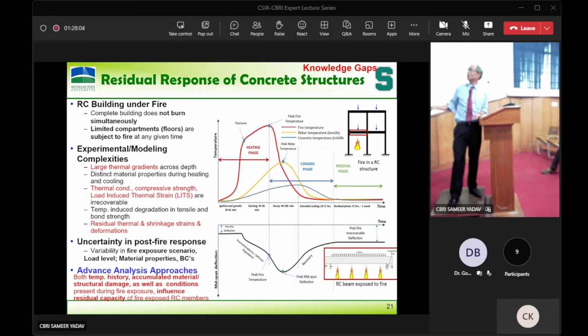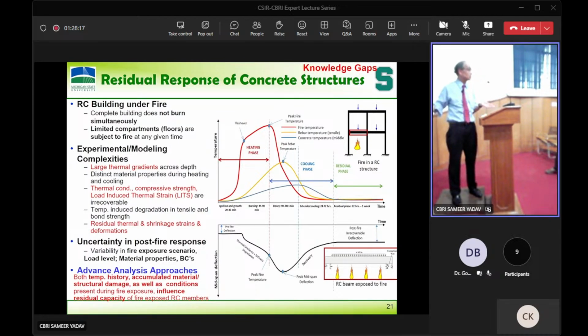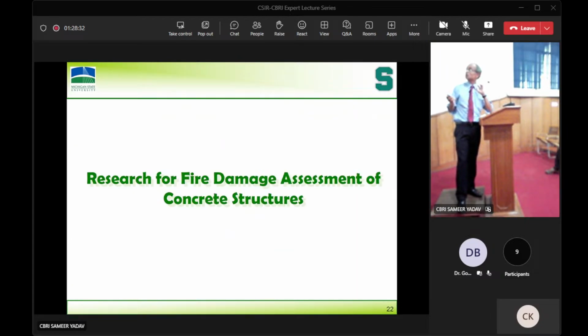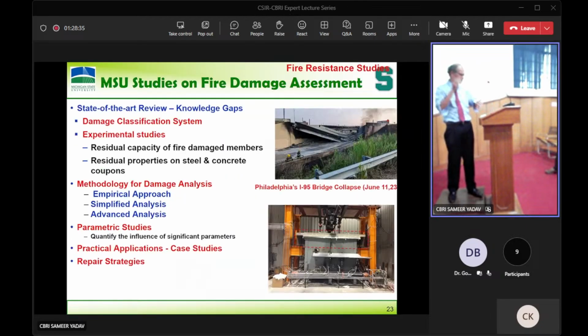Okay, somewhere there. Now, the deformation: in the first 15-20 minutes, nothing happens. Then slowly deformations increase. But since it's cooling, with a certain lag, it starts to regain its strength. Then it goes up. This is the residual. So finally, you end up with residual deformations, and when you have residual deformations, the capacity is very complex to model. It's not easy. So we have done a lot of work over the last decade or so, as I mentioned to you, on this subject with significant funding.